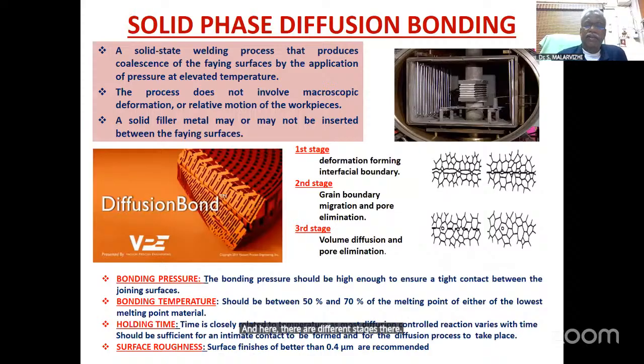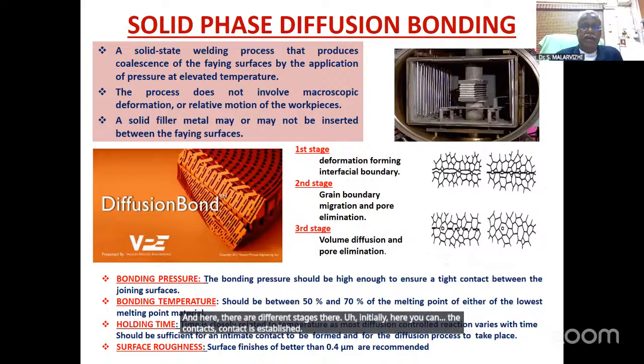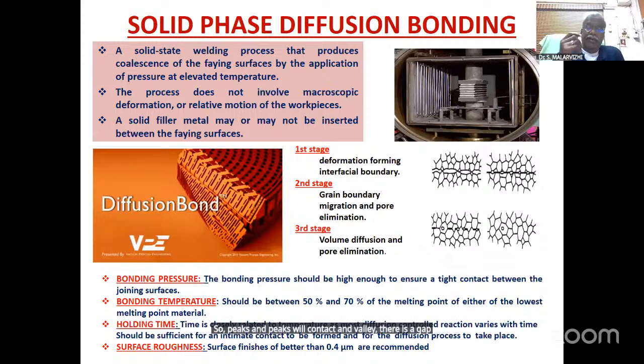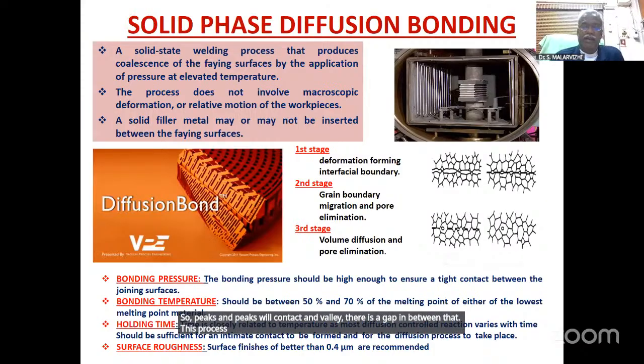Initially, the contact is established, because whatever you do, the polishing and other things, there are asperities on the surface. So peaks and peaks will contact, and in the valleys there is a gap in between. This process involves pressure and temperature you have to apply, and you have to give sufficient time also.